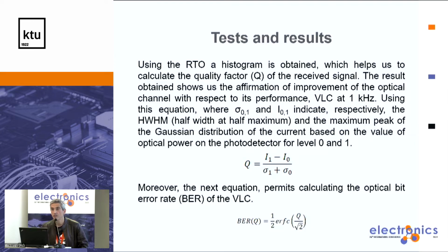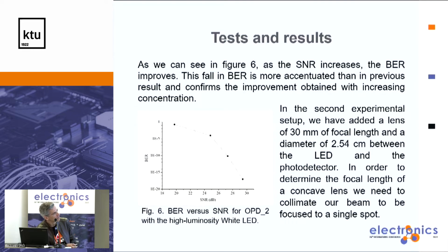Well, the use of the RTO, the real-time oscilloscope, is important because with the histogram, it's possible to obtain the quality factor of our received signal. So 2 minutes, yeah, I can do it. With the histogram, we can obtain the half width at half maximum and the value of the level 0 and 1. We can obtain the Q factor, and with the Q factor, we can obtain the bit error rate, the optical bit error rate. So here you have the results related with the bit error rate when using the first configuration.